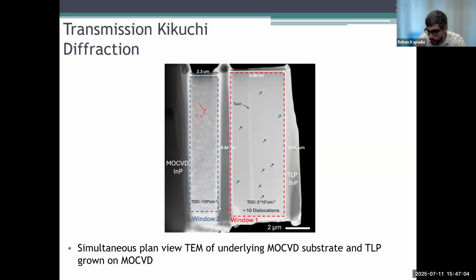And then when you go to the material that we're growing on top of them, you're getting maybe 100x, potentially 1000x reduction in defects just by having one single interface. And that is something that is extremely unexpected. We would not have expected that. But in fact, it does happen.